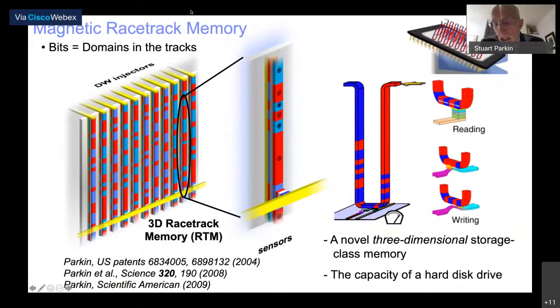So the basic idea, shown in this cartoon, is that you have a magnetic nanowire, the racetrack, which is homogeneous, and in which we can create magnetic domains in red and blue directions, basically up and down, and the information is encoded in the domain walls between the blue and red regions.